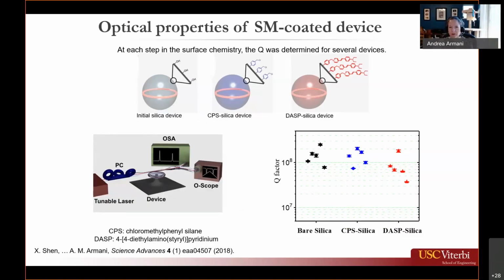So for the first exploration, we decided to use microspheres because they're much larger, much easier to use, and much easier to do surface chemistry on. So if you start with your initial silica device, then coat it with a silane chemistry, leaving a reactive chlorine group on the surface. We then anchored something called DASP, which is a pyridinium-based nonlinear material, onto the group. Now this step was very critical. Having this ordered monolayer on the group is very distinct from doing something like spin coating or dip coating, where you end up with a disordered monolayer that is perhaps multi-layer, so not a monolayer.